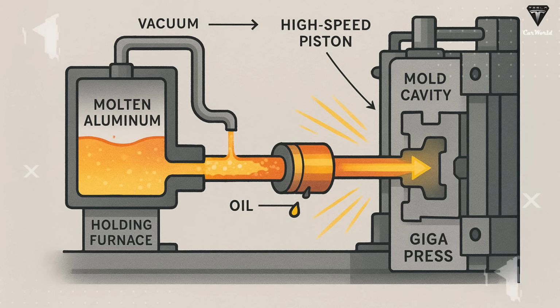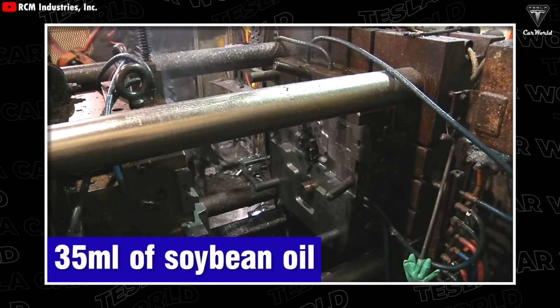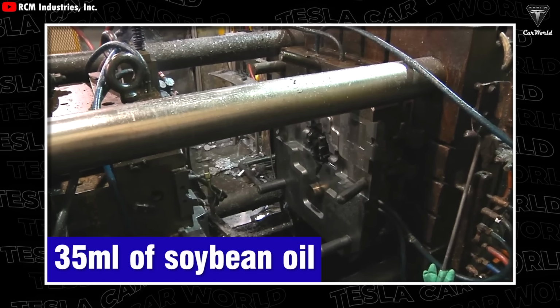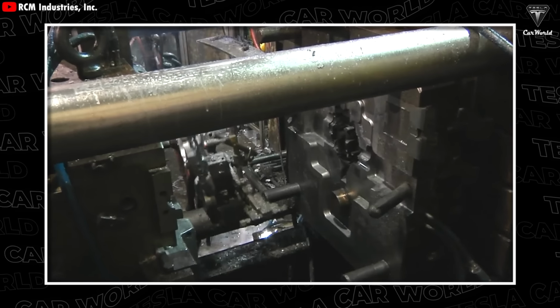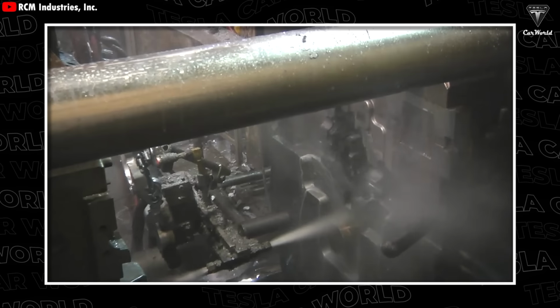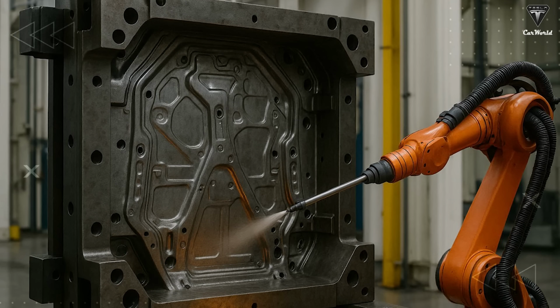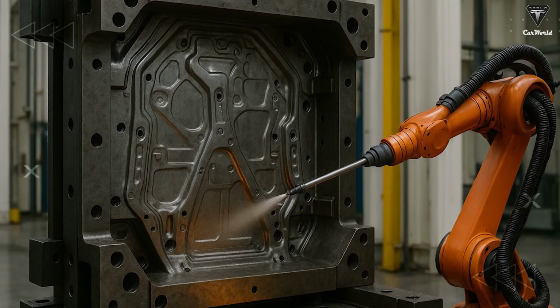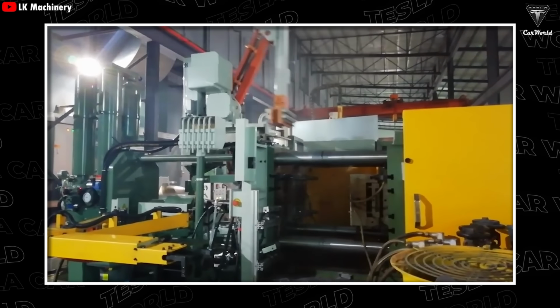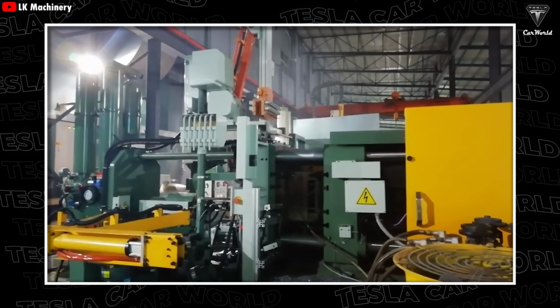This is where things get particularly interesting. A robot sprays about 35 milliliters of soybean oil as a thin, even layer across the mold. Yes, it's similar to greasing a baking pan so the finished product can be removed easily without sticking. After that, the system creates a vacuum to remove any remaining air, and the molten aluminum is transferred from the holding furnace into the shot chamber of the Gigapress.